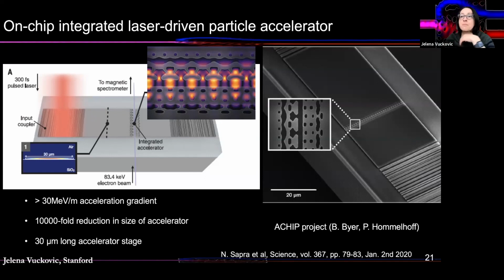And here we've shown an on-chip integrated accelerator, again, enabled by inverse design. You see these non-intuitive patterns here. It's 30 micrometers long. We designed this element so that the electromagnetic fields coupled through a grating coupler, propagating here, would accelerate electrons that are incident from a converted scanning electron microscope. And this non-intuitive structure here basically acts in such a way that it produces the field pattern that always accelerates electrons, which are incoming with a particular energy. So that's 83.4 kilo electron volts in this case. The stage is 30 micrometers long. And here we use a 2 micrometer laser wavelength for acceleration.